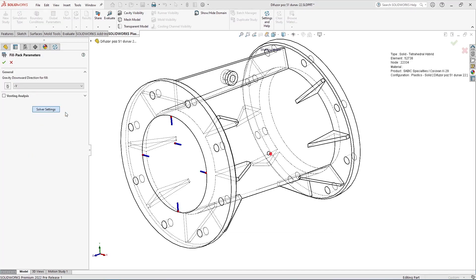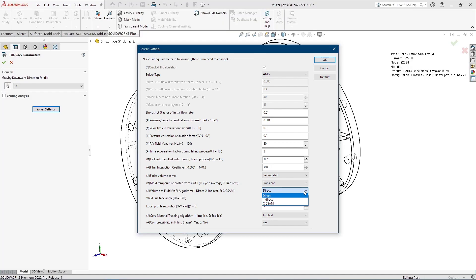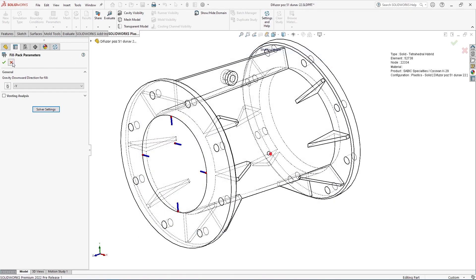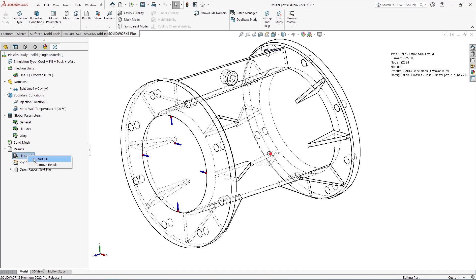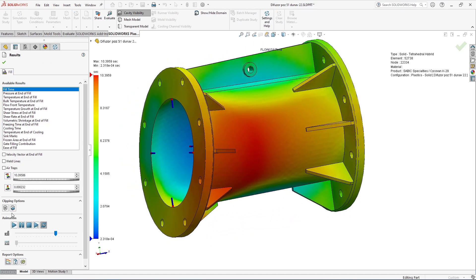The direct solver is an option under the solver settings for your fill analysis, which gives you the most accurate fill pattern, although historically it had the longest solve time. However, the solver was recently improved, and on average the solve time for a fill analysis using the direct solver has been reduced by anywhere from 30 to 70 percent, depending on part design. That means it's going to be faster than ever to pinpoint where your gate should be located, and what the resulting fill pattern will look like — and whether that filling pattern will result in weld lines, air traps, sink marks, or other potential defects.